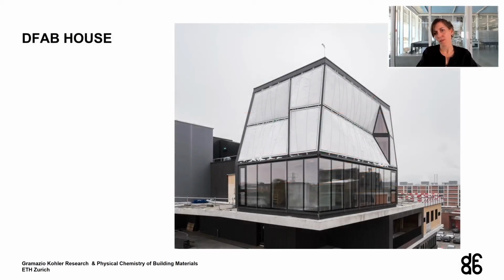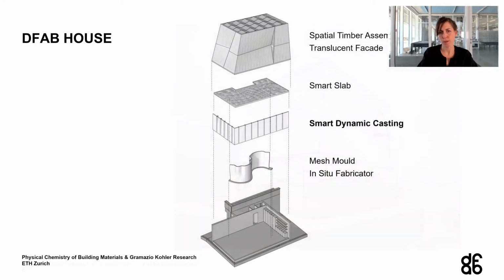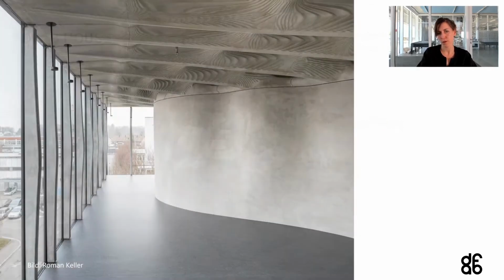So this success of having a structurally optimized column was the reason why we were invited to take part in the DFAB house at the EMPA in Dübendorf in Switzerland, where 6 different innovation objects were placed together into one unit to show how digital fabrication can actually change the way we build and become more sustainable for our future. It started with the mesh mold and the in situ fabricator, which most of you are familiar with. Then we have the smart slab, and on top of that, the spatial timber assembly structure that was prefabricated at the ETH in Zurich and closed off with a translucent aerogel facade. And finally, the smart dynamic casting mullions, of which we produced 15 individual ones that were reinforced.